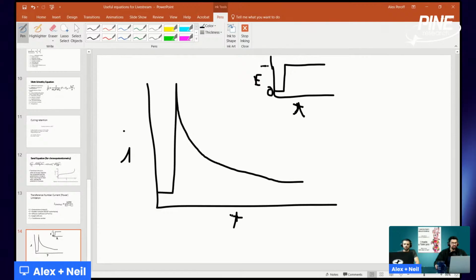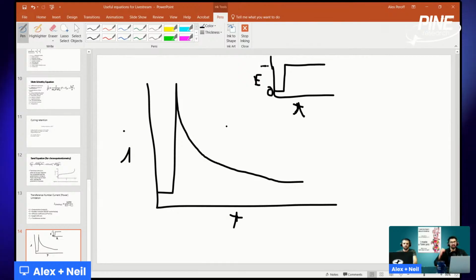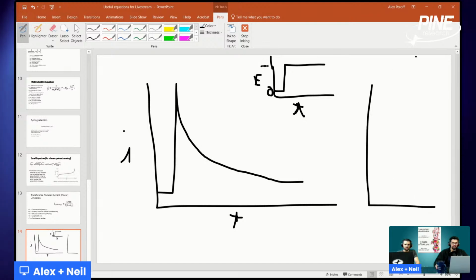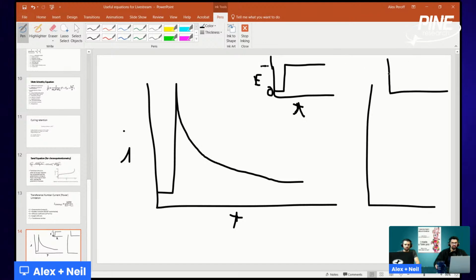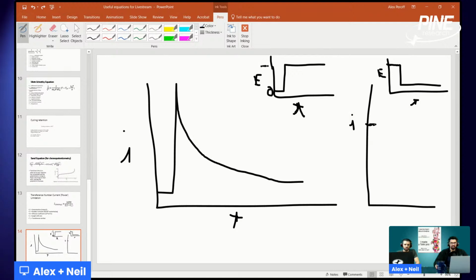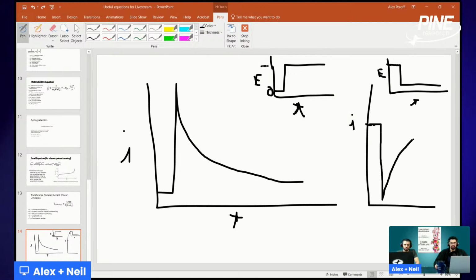And this fits what's called the Cottrell equation. So that's the case where I set the potential, I'm measuring the current versus time, and I see an initial spike, followed by a gradual decay in the current. Now, alternatively, if you're doing a reduction reaction, then this is flipped. Your E is here, and then you step the potential down, and now you're here. In that case, if your current was at a certain level, maybe 0, it would go down, boom, like that, and then slowly start to increase.